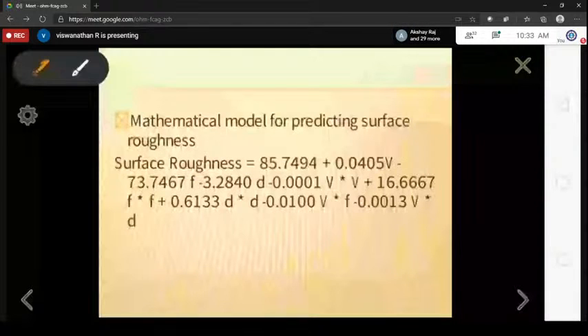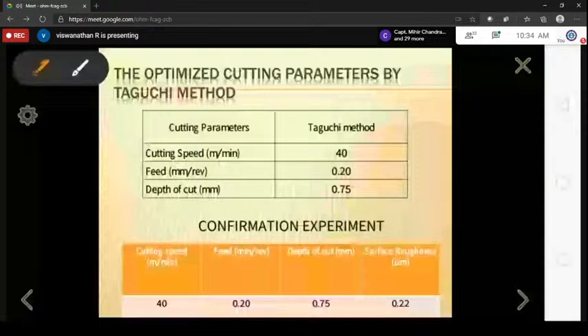After the experiment, using response surface methodology, we developed a second order quadratic response model for the surface roughness value to predict the roughness. Based on the response table and response graph, we got the optimized cutting parameters for the turning of magnesium alloy: cutting speed of 40 meters per minute, feed rate 0.2 mm per revolution, and depth of cut 0.75 mm. Based on these optimized cutting parameters, we conducted the confirmation experiment, and we got the minimum surface roughness value of 0.22 micrometer.